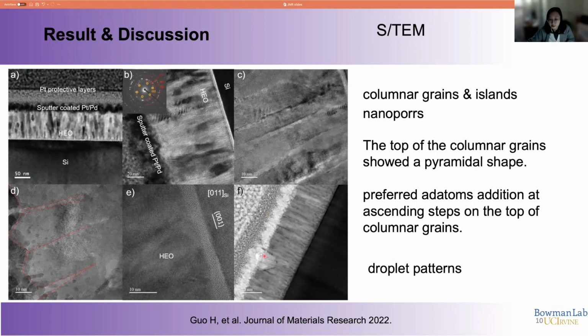In figure F, you also can see some droplet patterns that were introduced by the melting particles in the plasma during the deposition, when the laser hits the surface of the target. Besides the plasma, some material just gets melted so they produce small liquid, and the liquid will also jump to the substrate surface and deposit on the surface. It's a part of the films, which is a disadvantage for film application using the PLD, since these droplet patterns destroy the local structures of the films.